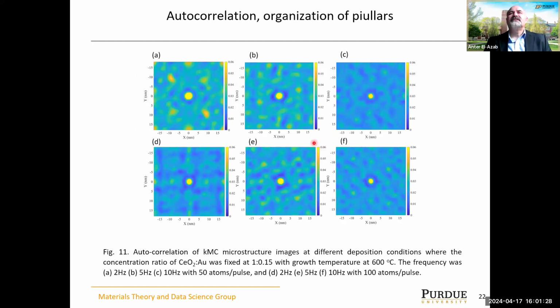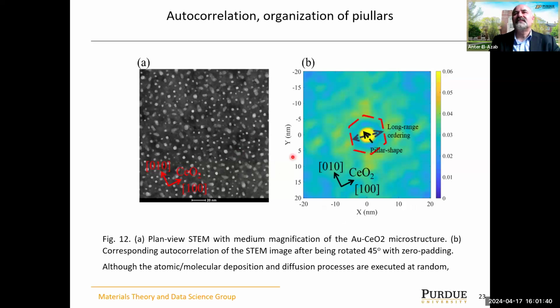We looked at the self-organization of these pillars in terms of the spatial correlation of these pillars on the surface, and we got something that looked similar to the correlation that has been analyzed for actual experimental micrographs here. Especially, from these correlations, we see the higher density of these 2-point. You can think of it as a 2-point density as a function of oriented distance. And the peaks here represent directions where you get more correlations. So it's indicative of how the pillars are organized on the surface itself. The zero distance here, or the core part of this correlation, has to do with the fact that it is the correlation of pillar material within the same pillar itself.